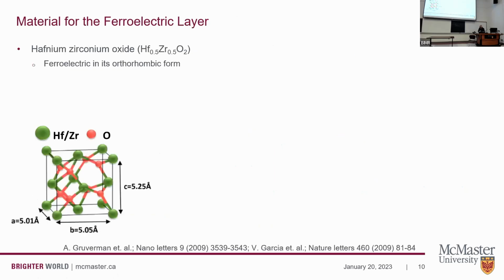But now, which material for this ferroelectric layer? We identified a compound made of hafnium zirconium oxide as one of the strongest candidates for that. And that's what we synthesized and used for artificial synapses. Why this one? Because it is ferroelectric in its orthorhombic form, which corresponds to its crystal structure, so the arrangements of the atoms in the crystal.